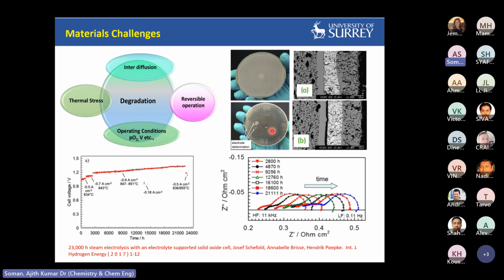You could see the real images. This particular image is from Sunfire, Germany. So they are working on the planar cells. They keep on reporting the delamination or degradation of the electrode surface, and the SEM images also confirm that you can clearly see the delamination, or the kind of crack, from the electrodes and the metallic layer. So these are the critical issues, and of course we will be monitoring the cell voltage versus